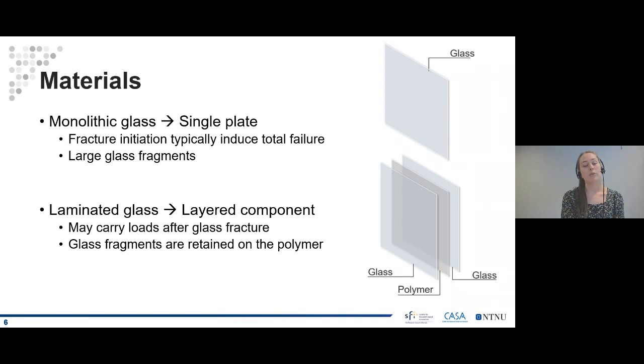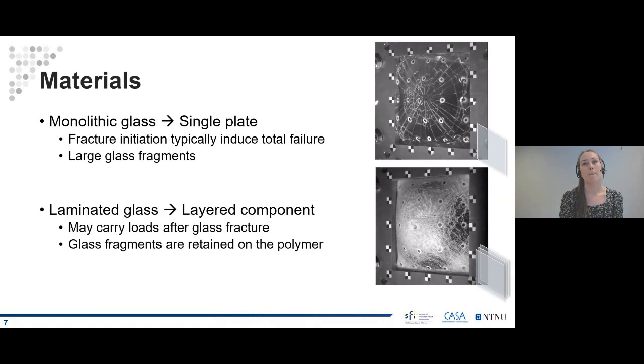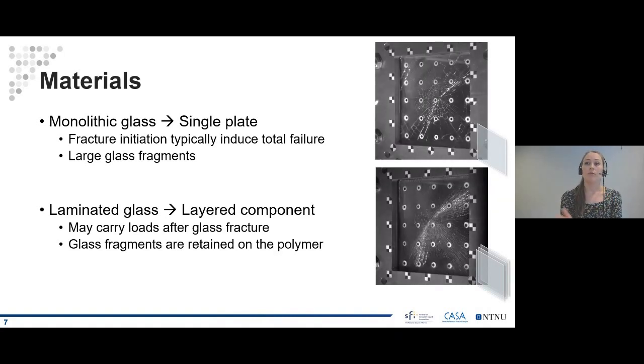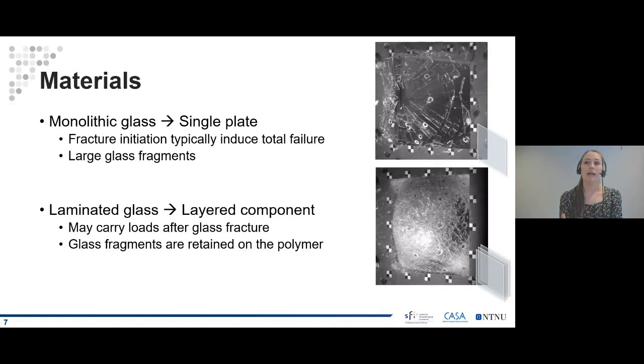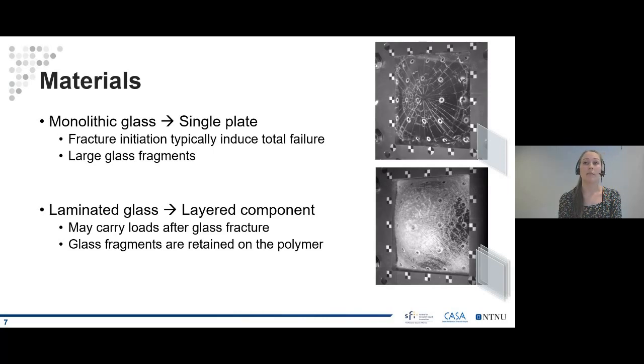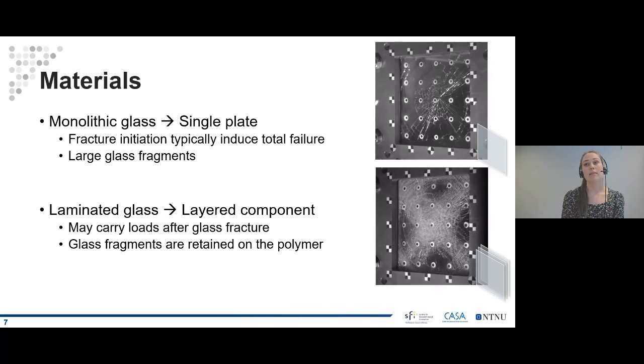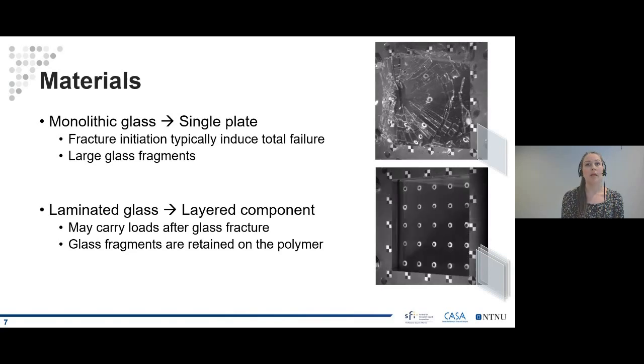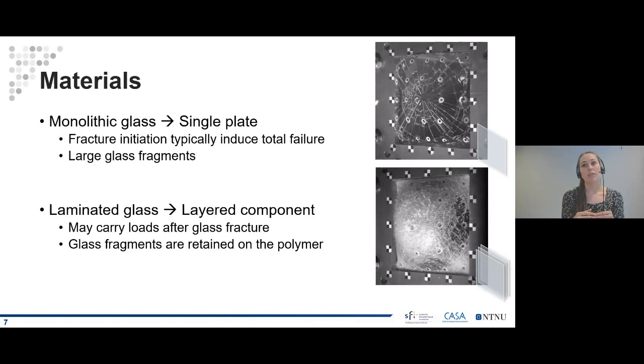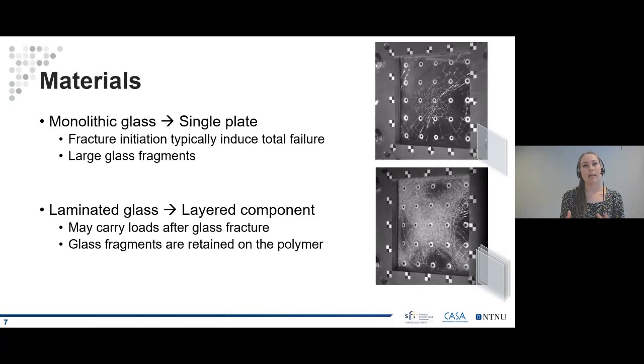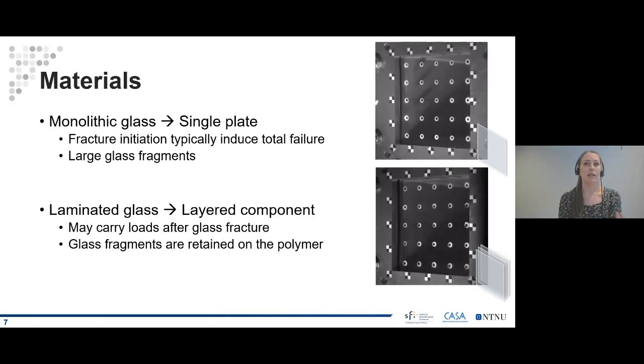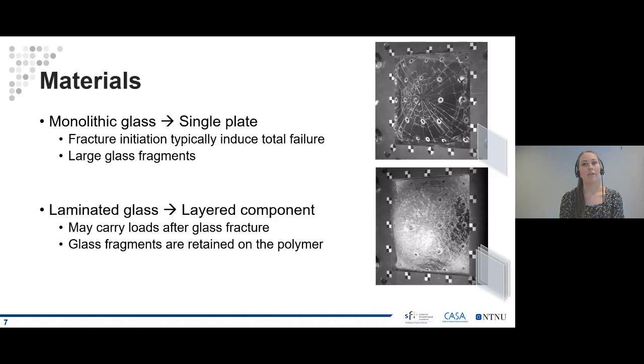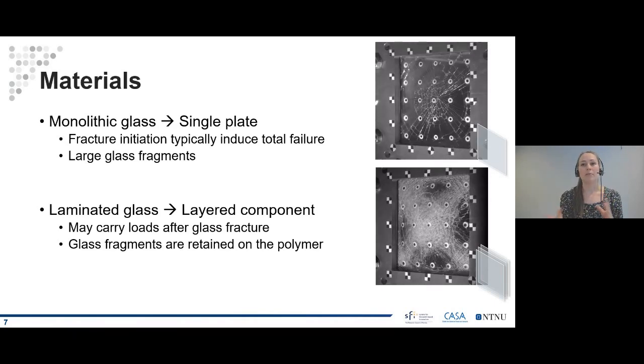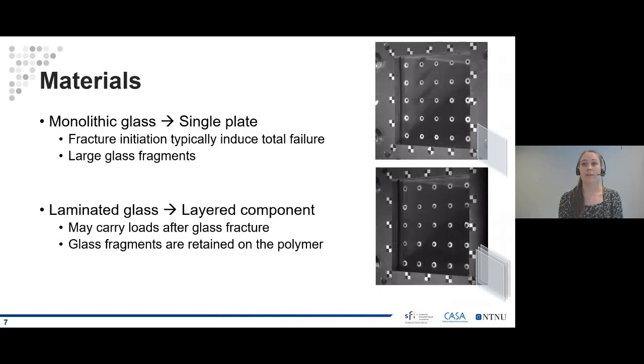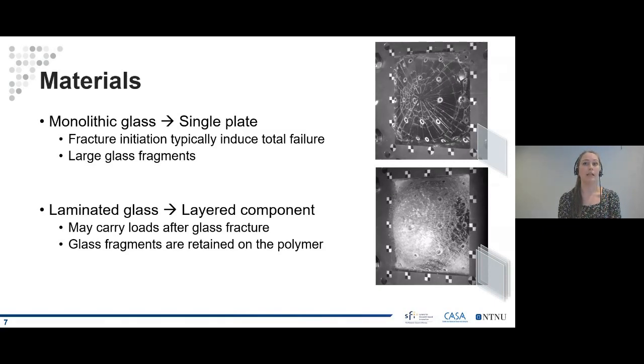The difference between these two glass types under loading can be illustrated by these videos. Here both glass plates are exposed to blast loading, and we see that the monolithic glass creates large and dangerous glass fragments, and for the laminated glass, the fragments are held back by the interlayer. We also see that the glass breaks into much smaller fragments, and we get some delamination, so detachment of glass fragments, but these are very small and very few. From these videos, we see that laminated glass is a much safer solution and is therefore often used in blast design.